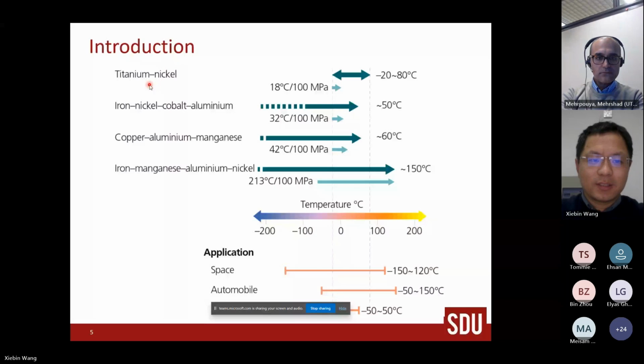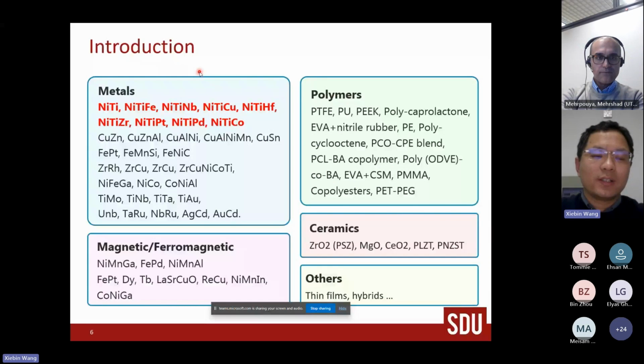In order to tailor the transformation behavior and to widen the application of binary nickel titanium alloys, people add ternary elements to modify its transformation behavior. For example, adding iron to nickel titanium lowers the transformation temperature, adding niobium widens the transformation hysteresis, adding copper narrows the transformation hysteresis, and adding hafnium increases the transformation temperature. These are called high temperature shape memory alloys.